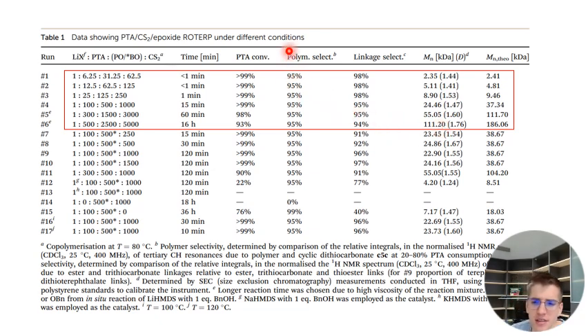The polymer selectivity with regards to the small molecule stayed approximately the same, but the linkage selectivity went somewhat down. And I defined here linkage selectivity of this new ester trithiocarbonate alternating sequence to thioester linkages. This is how I defined it. You can also define it in a different way. But what was relatively nice is that we could reach high molecular weights of 110.